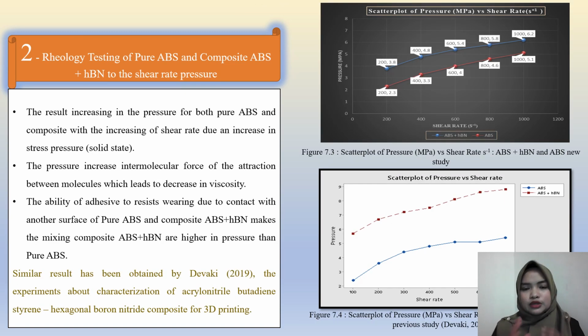And then the second one is rheology testing of pure ABS and composite ABS HBN for shear rate versus pressure. The result shows an increase in pressure for both pure ABS and composite with increasing shear rate, giving an increase in stress pressure in the solid state. The pressure increase comes from the increase in the molecular force of attraction between molecules, which leads to a decrease in viscosity. The ability of the adhesive to resist wear due to contact with another surface, for pure ABS and composite ABS HBN, makes the composite ABS HBN higher in pressure than pure ABS. A similar result was obtained by Devaki 2019, in the experiment about characterization of acrylonitrile butadiene styrene boron nitride composite for 3D printing.